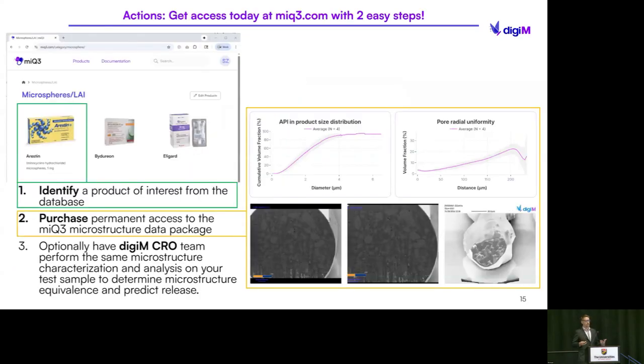So the way this database works is essentially you find a product that you're looking to test. In this case, I highlighted a microsphere. You identify the product of interest, and you can compare against all of these different features that we quantify. So API size distribution in the final product form, PLGA grade that was used in it, pore radial uniformity. You can see the actual images of the materials we've collected there.